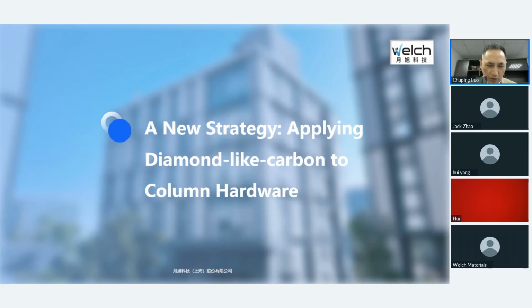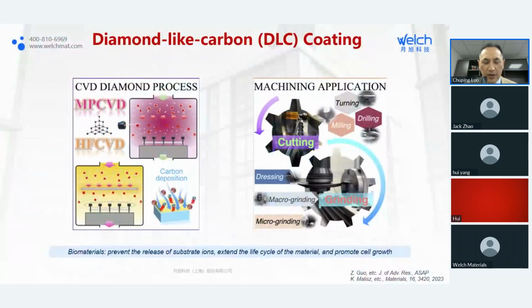So this picture basically shows you there are two different ways to create diamond-like carbon coating. On the top is microwave plasma CVD (MPCVD). On the bottom is high temperature. Either way, the diamond is gradually deposited onto the surface. And then people can use this to coat the surface for milling, drilling, cutting, grinding. All this is mechanical stuff. But people did find some unique applications. They coat this onto biomaterials. Biomaterials using this kind of coating can extend the life cycle of the material and promote cell growth. That's really good.